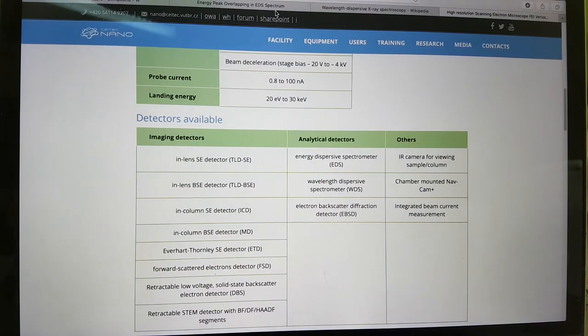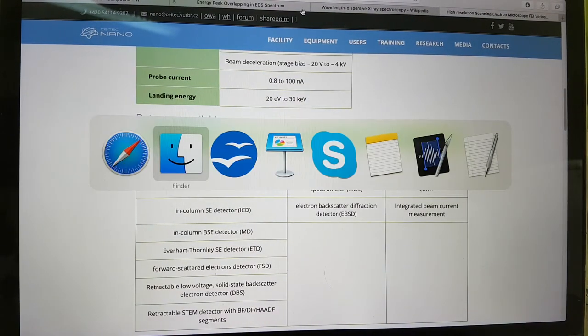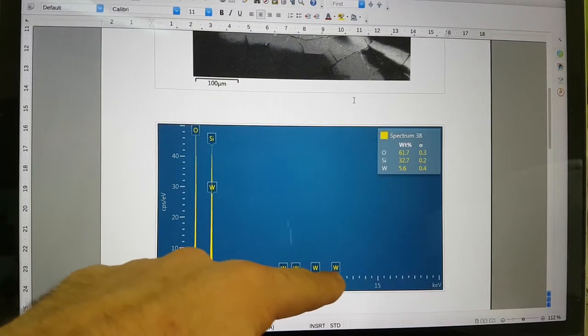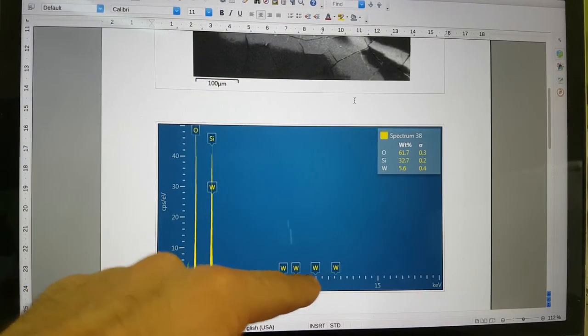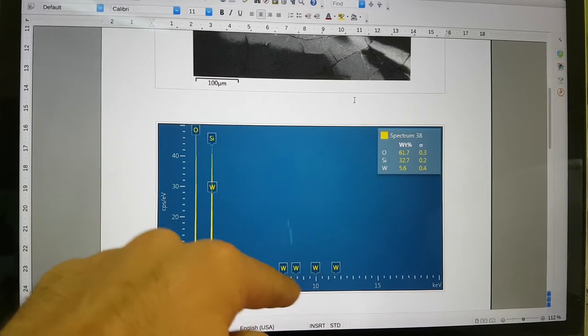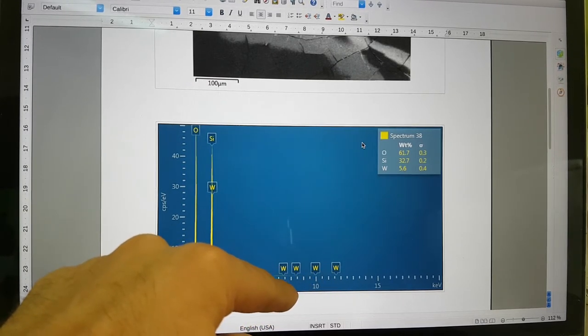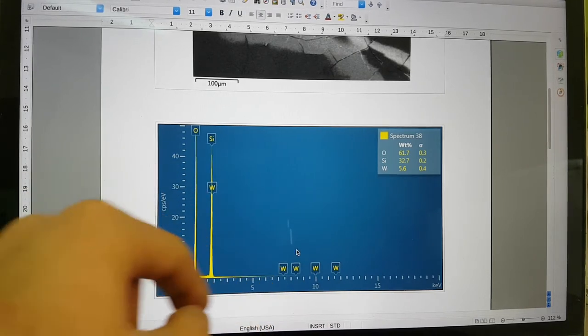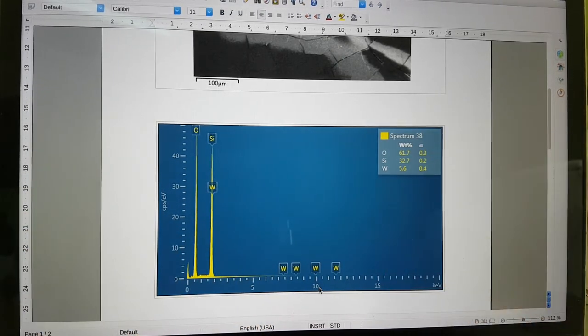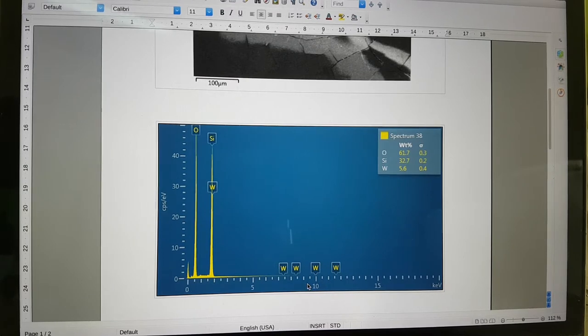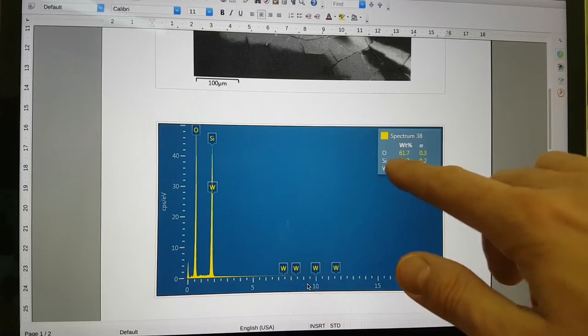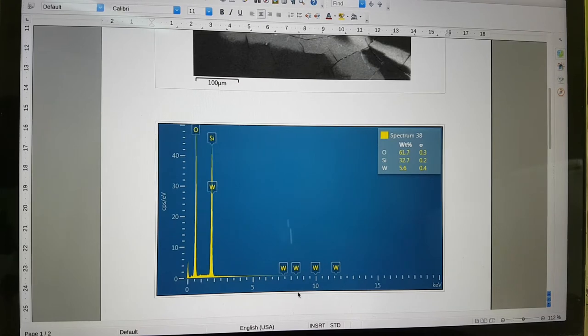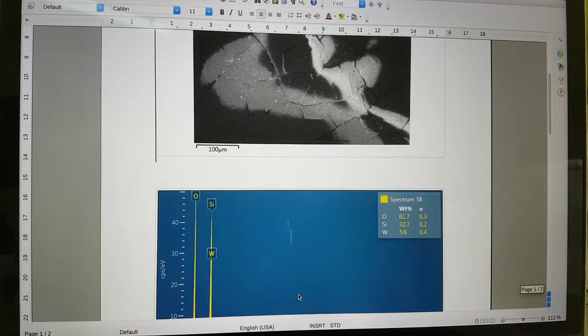But there's another thing that we can look at on the data that we have here. And that's when the peaks are not there at the higher energy levels, which they don't really appear to be. But we might not have the right amount of energy coming on to the sample from the electron beam. But it doesn't really appear that they're there. So it really does look a bit like silicon oxygen. But WDS should be able to pick that out.